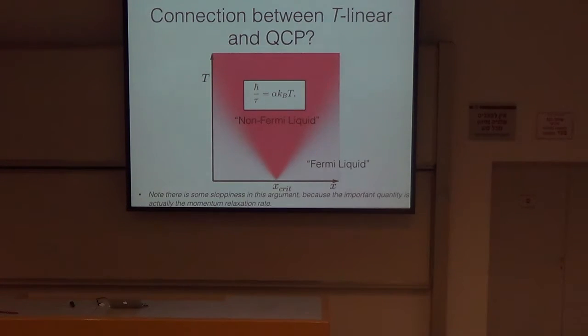But the essential idea is that because there's only one energy scale that goes into the scattering rate, it's often thought, or at least associated, that T-linear resistivity going down to the lowest temperatures is indicative of a quantum critical point, namely a point in the phase diagram where all other energy scales vanish. And the basic idea is that then there's only one energy scale that can possibly set things like the lifetime of the quasi-particle, and that is, of course, temperature.